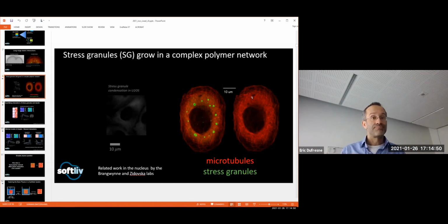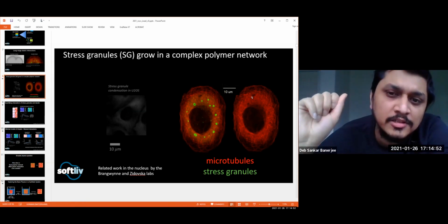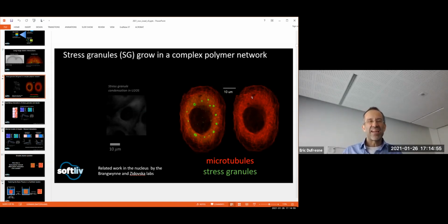So because of the pressure and the cavitation instability. Yeah, and also, I was trying to make a simpler point. The simpler point is that if I take a slab of a polymer network and describe its structure statistically at the mesh scale, there's a huge amount of variance. But if I zoom out and coarse grain and look at a larger volume, there's much less variation from point to point in a material at larger scales, right? So the concept of Young's modulus makes a ton of sense at the micron scale, but it doesn't make any sense at all at the nanometer scale.